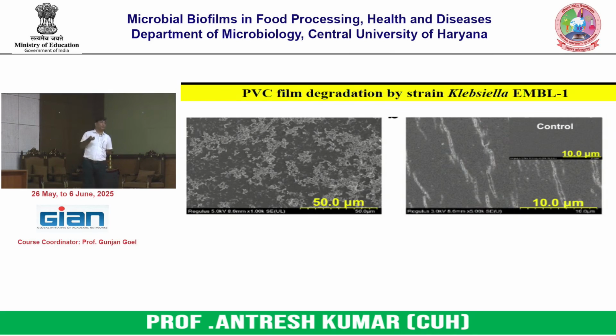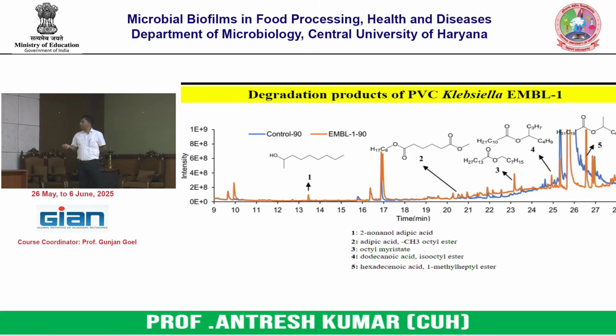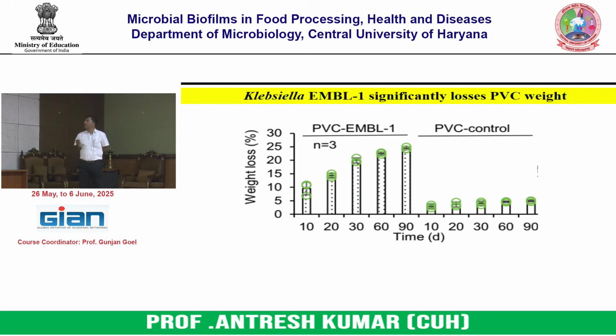This is the only report I found for PVC degradation, that is Klebsiella EMBL1, which can efficiently degrade polyvinyl chloride. So this is the control, which is the polyvinyl chloride in the medium, and this is the bacteria grown, the Klebsiella, which can disturb the structure of PVC when grown on this surface. So this particular strain can efficiently cause weight loss.